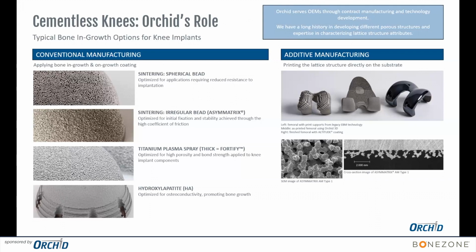So the offerings we have geographically are located in 3 different places for porous structures. One is based in Memphis, where we apply all of the sintered coatings. The other 2 are in Detroit facility and in our Switzerland facility. Those facilities apply porous structures via plasma spray. So titanium coatings are applied using vacuum technologies, vacuum plasma spray, and HA is applied via atmospheric plasma spray.